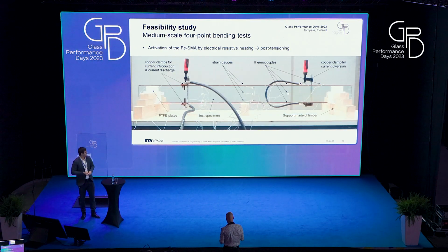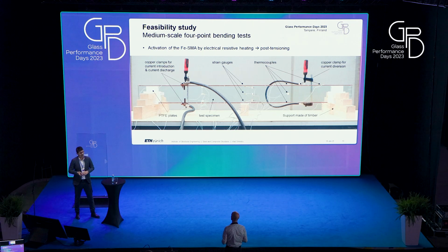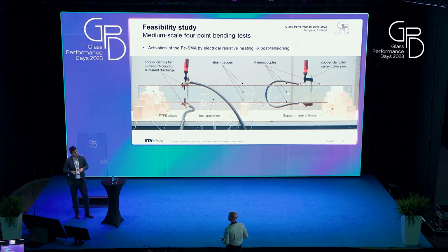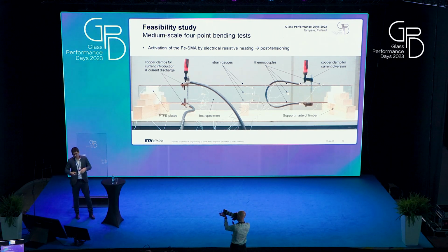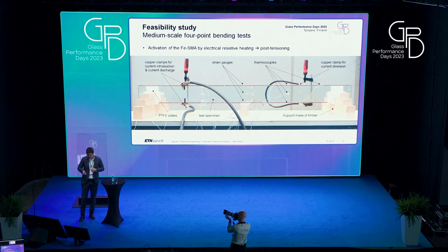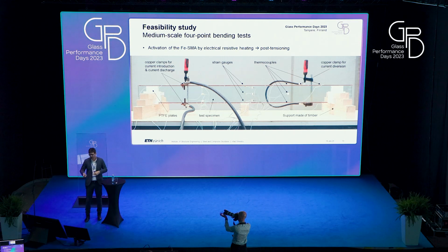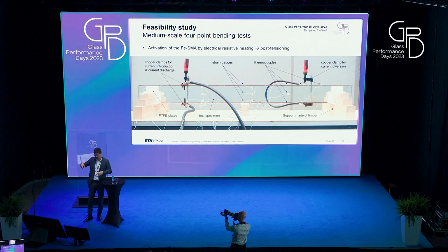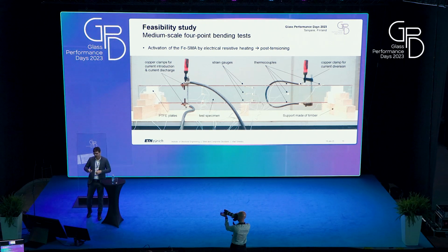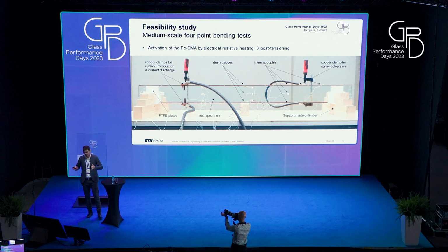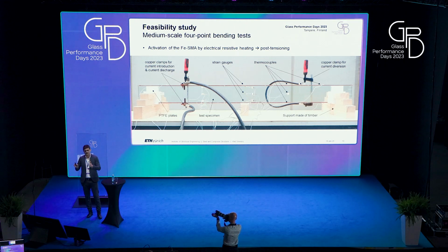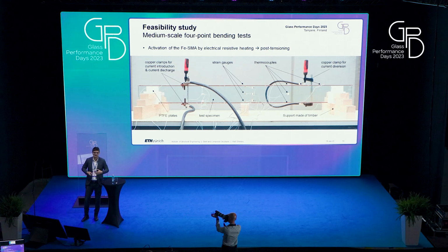You can see here the setup we used for activation. We did it by so-called electrical resistive heating, which means we apply an electrical current. You see it on the left side with these copper clamps. The current flows to the right side, is diverted to the bottom strip, and flows back to the left side. The idea is that the current and the heating happen only in this middle part of the beam, not in the anchorage areas, so the adhesive there is not disturbed in any way.